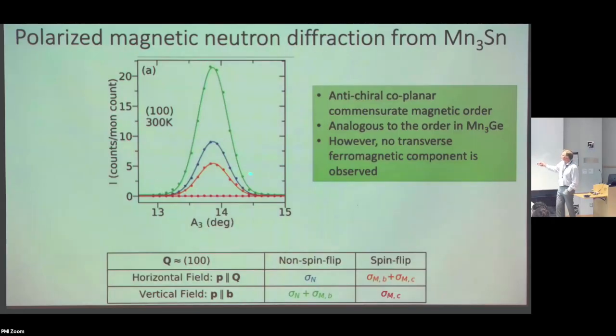in very different colors that corresponds to various different channels of polarization. So for part of the experiment, I'm having a horizontal guide field, which makes sure that the incident neutron is polarized along the wave vector transfer. That's this row here. And for part of the experiment, I have a vertical guide field, which makes sure that the incident neutron spin is polarized perpendicular to the scattering plane. We keep track of the incident neutron, and we choose specific orientations that allow us to bring out specific